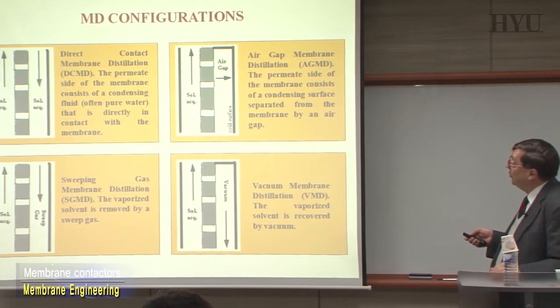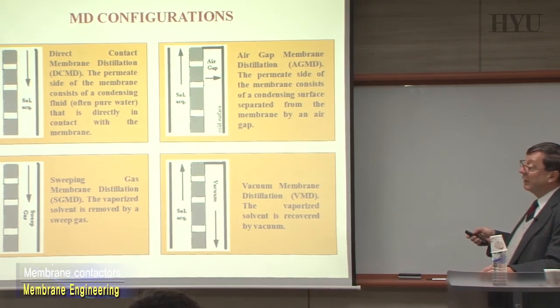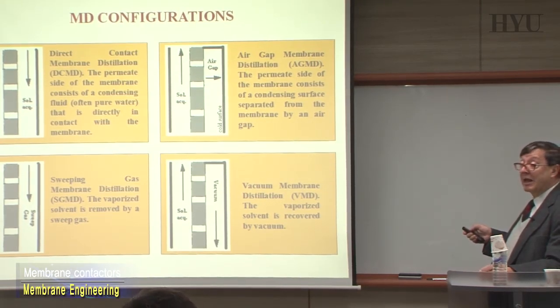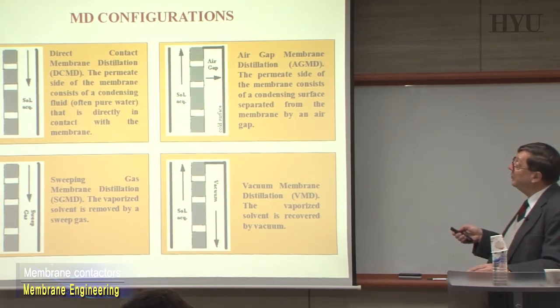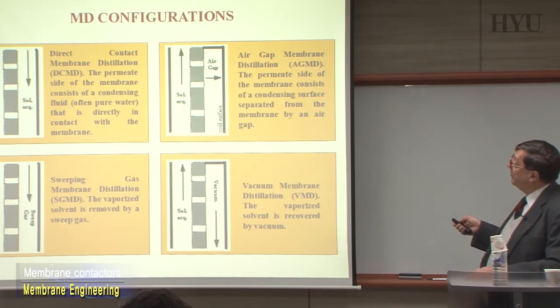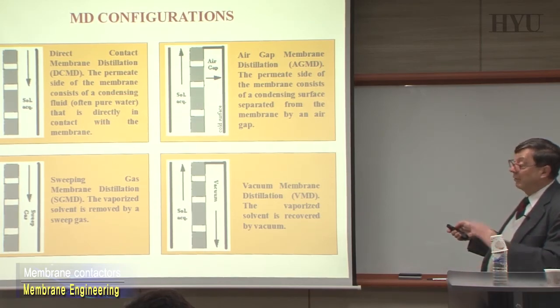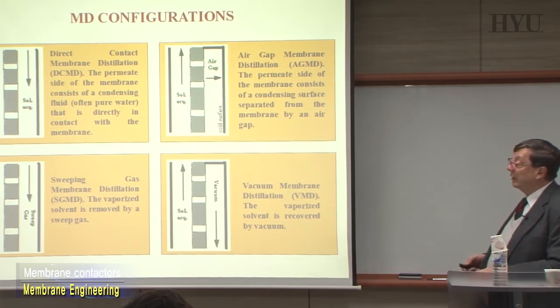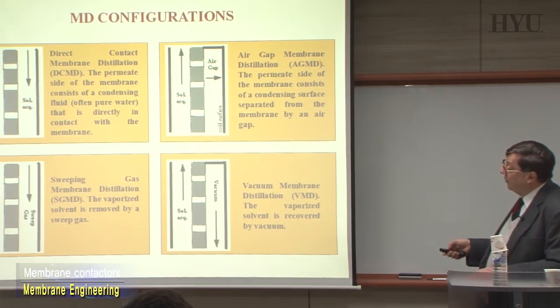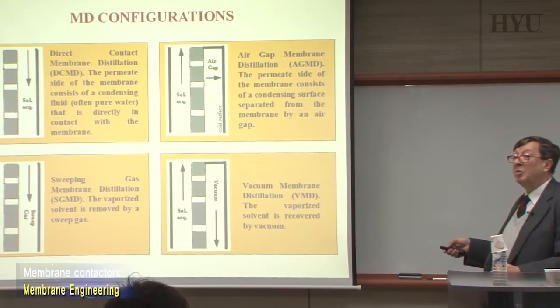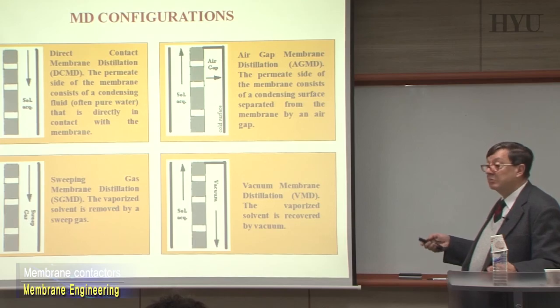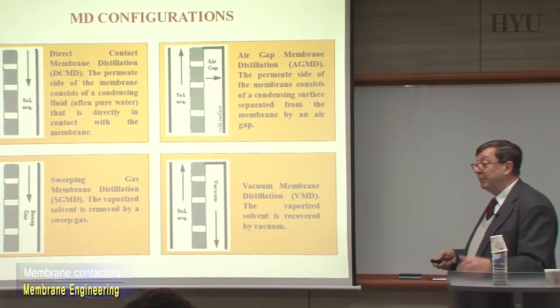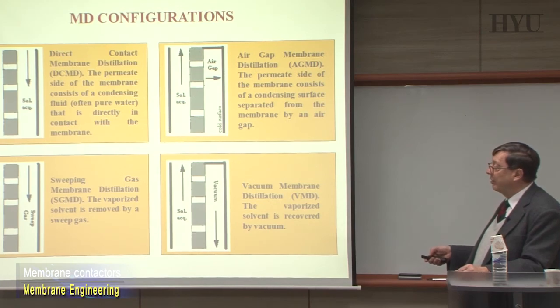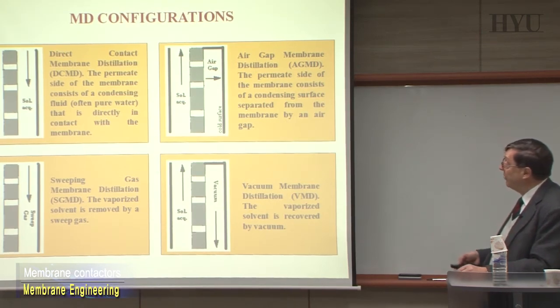You can have another system in which, on the permeate side, instead of a liquid phase, you have what we call an air gap. You have just air, and a condenser at a certain distance from the bottom side of your membrane. So here in the middle is the air gap. The permeate side is a condensing surface separated from the membrane by an air gap. Instead of just an air gap, you can have another configuration where you introduce a sweeping gas. Here you have a sweeping gas that is circulating, and this helps to extract the water. So the vaporized solvent is removed by the sweeping gas.